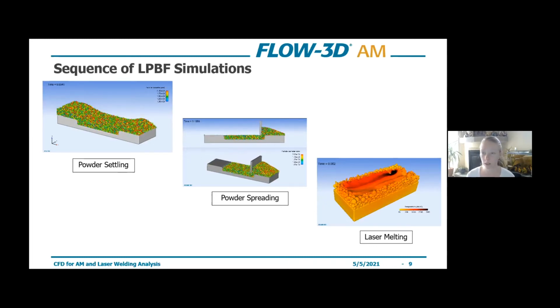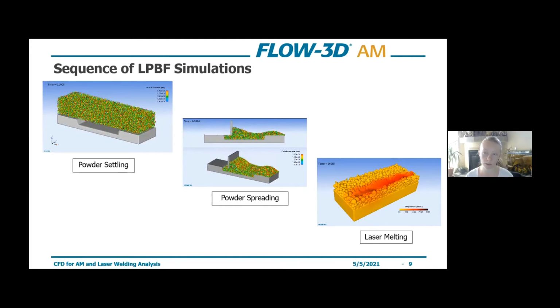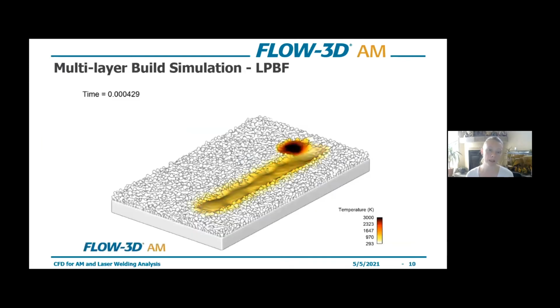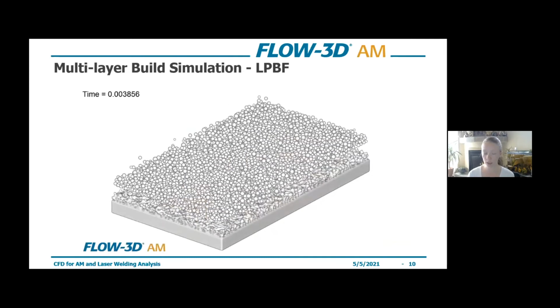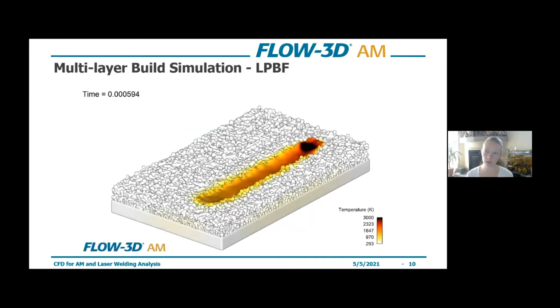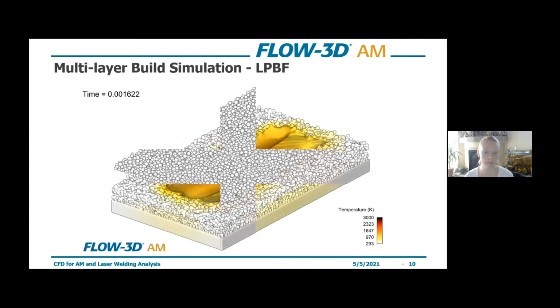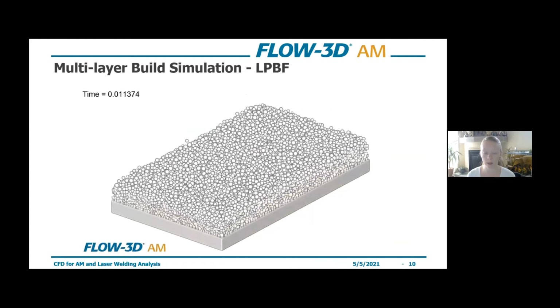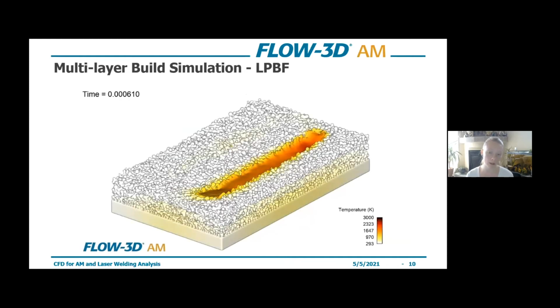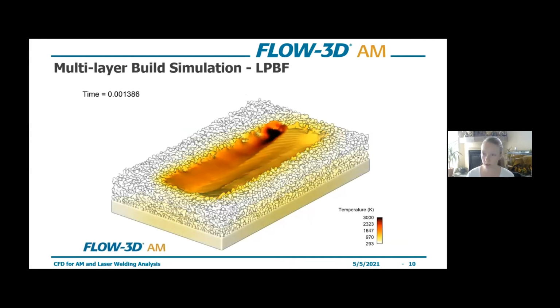So we're still getting very good information about the effect of processing parameters on the result, despite the fact that we're not quite accounting for that powder movement just yet. And ultimately, we're still working in the mesoscale range, so we can do a few different layers. There is a limitation just in terms of computational efficiency, and as time goes on, I'm sure that will improve. But right now we're looking more at 3 to 5 layers,